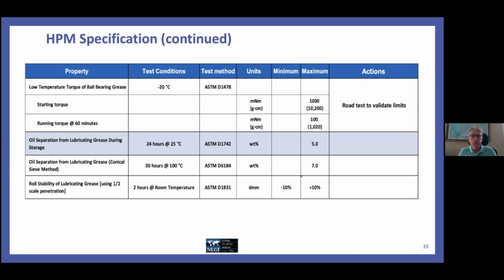Oil separation, another test for oil separation, the D6184, which we feel is a generally more severe test and adds another perspective on oil bleed than just the D1742. And for this test, we've got a limit of 7.0 compared to the D1742 at 5.0, recognizing that D6184 at 100 degrees C is a more severe test.